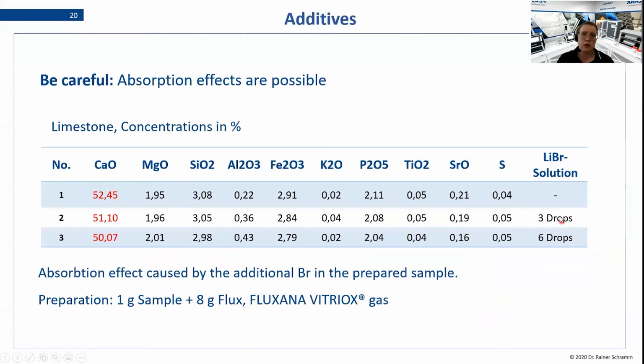Also, there are some absorption effects possible due to the addition of these halogens. Here we are having a limestone sample again, and lithium bromide solution was first not added, and we get a concentration of roughly 52.5. And the more bromide was added to the sample in more preparations, we can see that the concentration of the main component decreases significantly. And this is an absorption effect that is caused by the additional bromide we added into our prepared sample here.